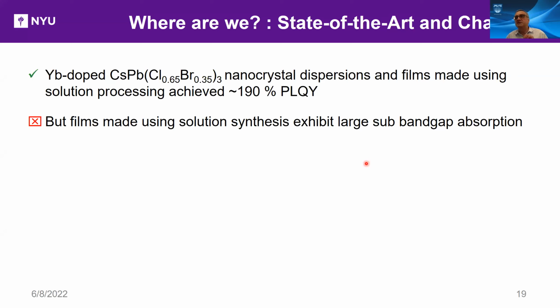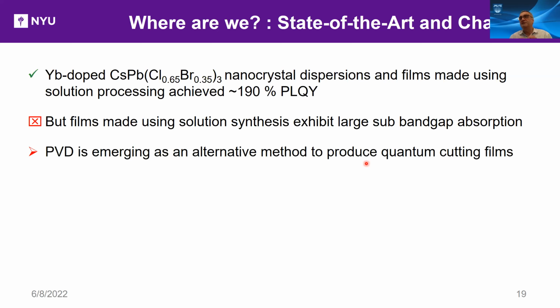Making films using solution synthesis, however, proved problematic. One big thing is that it exhibits large sub-bandgap absorption, so it absorbs things that you would like to get to silicon. That's one thing. And the solution synthesis is not necessarily very easily scalable with the synthesis techniques used for perovskites. There are all sorts of problems that have to do with solvent compatibility, the solubility of the precursors and things like that. So good old physical vapor deposition that those of us at AVS are very familiar with is emerging as an alternative preferred method to produce quantum cutting films.